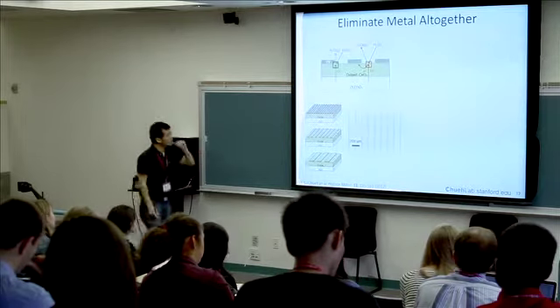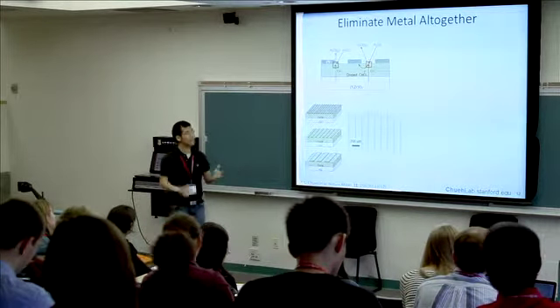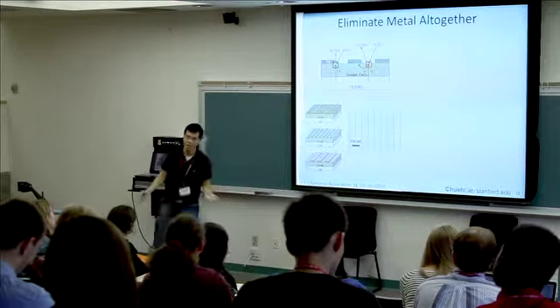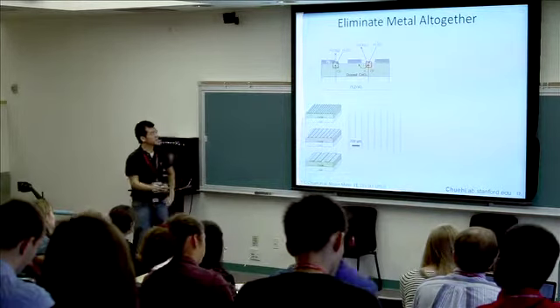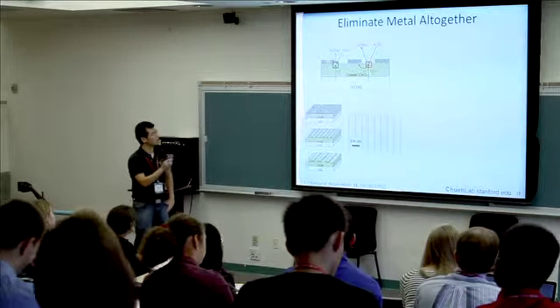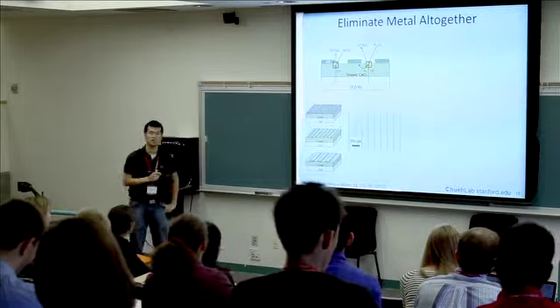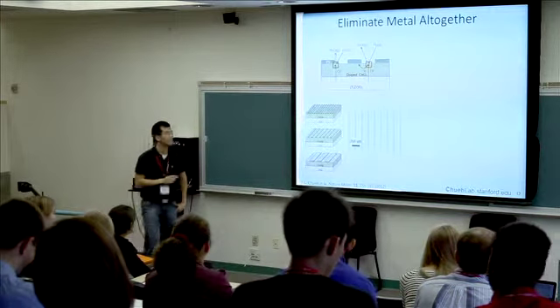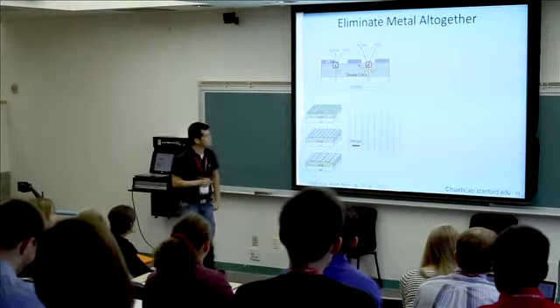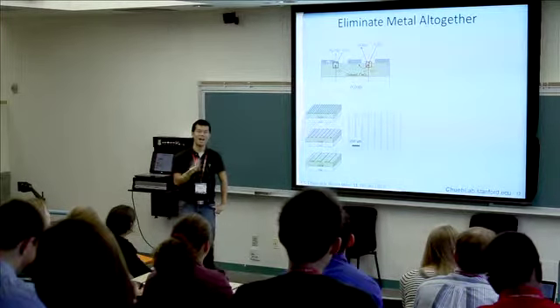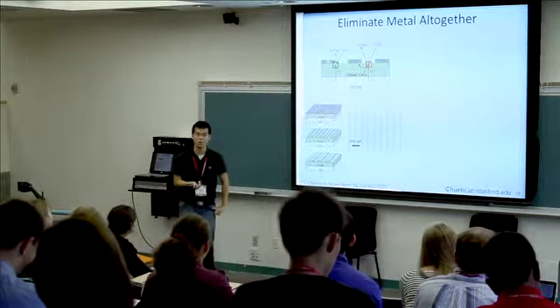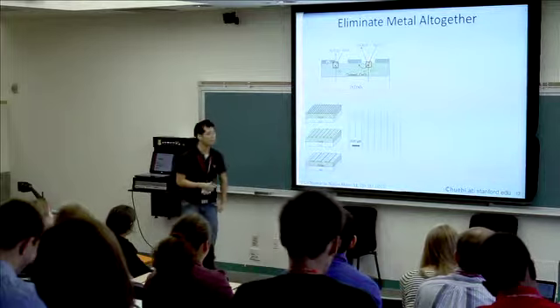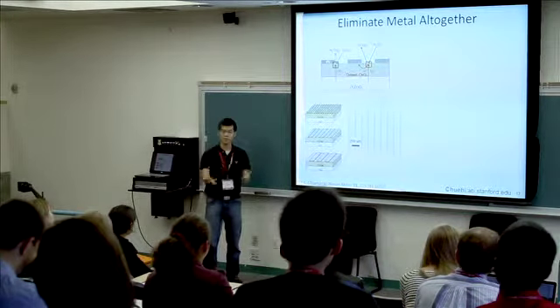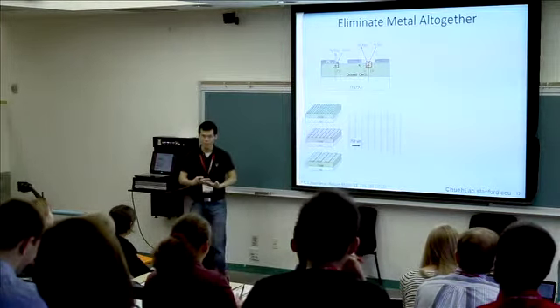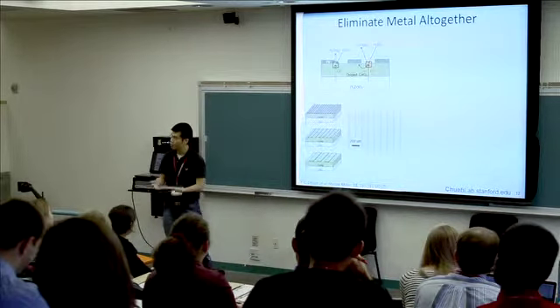So this is some work I've done in the past. We actually show it's possible to eliminate metal altogether when we go to this higher temperature. For example, we were looking at a material known as cerium oxide, which is already known as a good catalyst for fuel cells. But we did a very simple experiment. We wanted to know exactly how active cerium oxide is relative to platinum, one of the best catalysts. So what we did was we used lithography, and we made very well-defined features of platinum on cerium oxide.